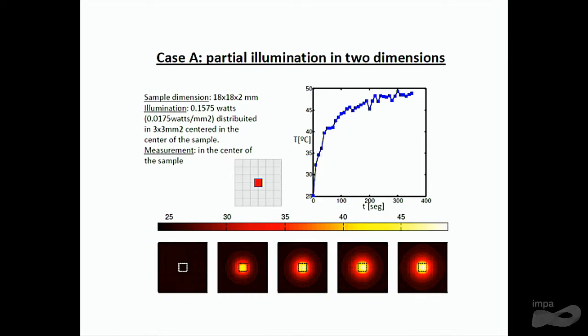sample. Here is a case in which the illumination, this is the typical sample we're going to use. It's a square sample in the XY dimension. It has a thickness of 2 millimeters, and is illuminated with a density of light of 0.0175 watts per square millimeter, and located in the center of the sample. And the form of the spot is a square. The form is not very important.